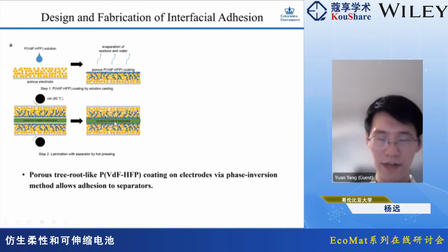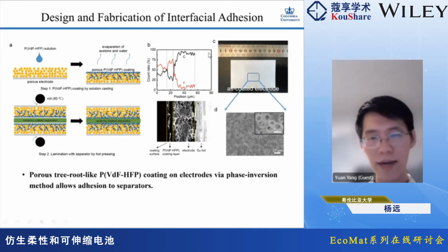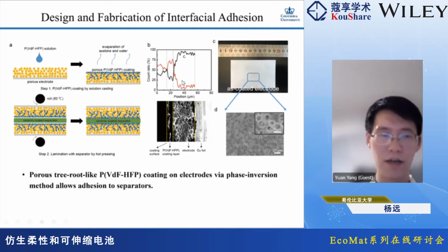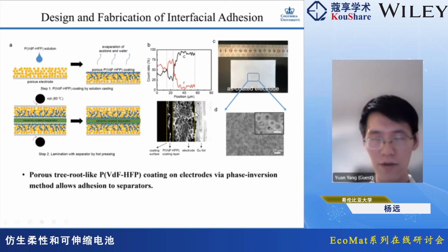So laminate all layers together. And if we look at the penetration of these polymers into the electrode, we can see the fluorine signals inside. Because we use alginate as a binder and graphite as the electrode, we actually have no fluorine from other components. So the existence of fluorine inside the electrode indicates we really have the polymers penetrating into the bottom of the electrode layers. And this layer is also porous. That means the electrolyte can also go deeply inside.